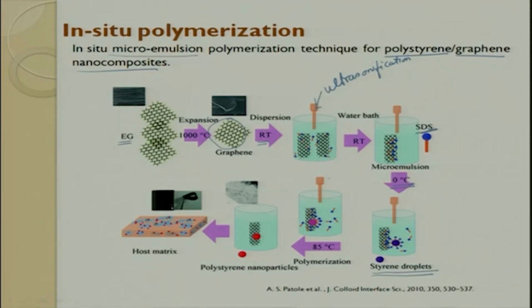So now these are the polystyrenes which are there. The polystyrene is made, and then we try to pour it inside a die or extrude it into a strip, whatever it is, to get the polymer nano composite - polystyrene graphene impregnated polymer nano composite for various applications. You can see the red dots are polystyrene, and the functional parts are also mixed, so graphene is also mixed. You get a host matrix, and then you get the final output.